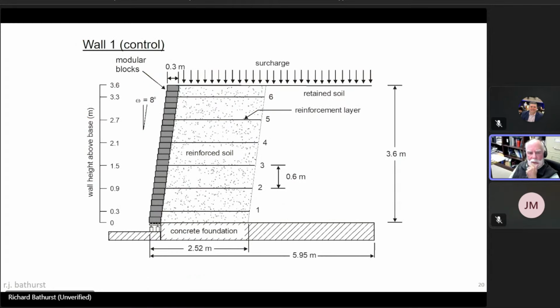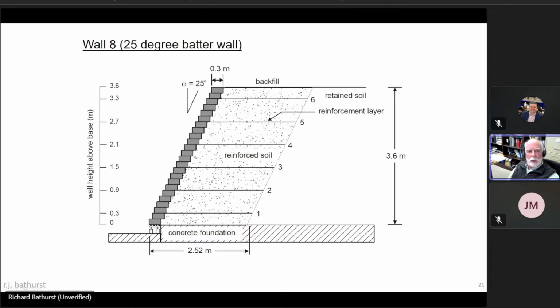So here we see a cross section of the control wall, and you can see the shaded area are the modular blocks. The facing was inclined at a batter of 8 degrees. And again, after the wall was constructed, it was surcharged in stages. Here is an example of one of the other walls. Again, it's a modular block facing, but now the facing batter has been increased from 8 degrees to 25 degrees. And the idea is that the difference between wall 1 and wall 8 could be largely ascribed to the effect of the facing batter.